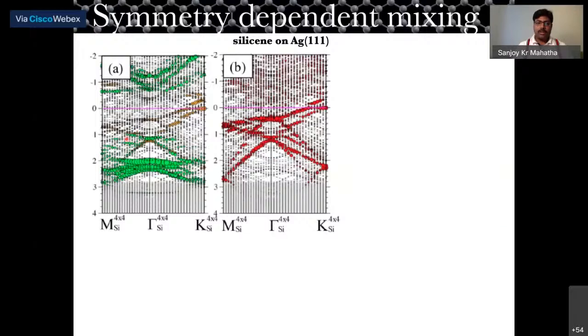And these are the calculations of silicon on top of silver 111 in a folded Brillouin zone. And you see some green bands. These are coming from silicon sigma orbitals, okay? And these orange ones are coming from silicon pi orbitals, or silicene pi orbitals. And these are projected on the silver 111, and you can see these are silver contributions. So if you say that there is a pi contribution in the band structure, then you can definitely say that these contributions are somehow set by this silver 111 band structure.